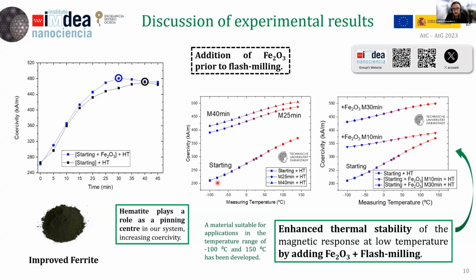The starting powder presents the usual magnetic behavior of the strontium hexaferrite while we increase or decrease the temperature. And here we can see the main problem of using these ferrite powders in magnet fabrication, for example, for the electromobility sector magnets. That is the risk of demagnetization when we go to low temperature environments. So what we propose is that the increase in coercivity reached just by flash milling could be effective to avoid this risk of demagnetization in these low temperature environments.